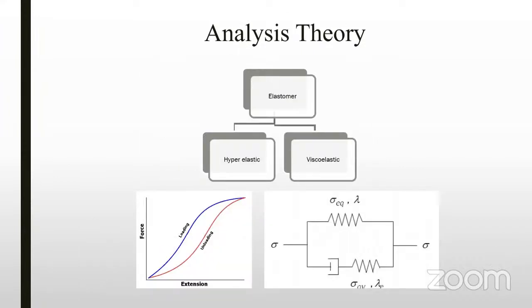The elastomers have two different behaviors: hyperelastic behavior and viscoelastic behavior. Hyperelastic behavior is related to the highly nonlinear behavior of these materials, as we discussed in the previous slide. And the viscoelastic behavior is related to the hysteresis, which we can see in the stress-strain curve of these materials during loading and unloading. In the previous studies, most of the researchers used the rheology model to simulate the viscoelastic behavior of these materials, which is time consuming and has some difficulties in calculation.